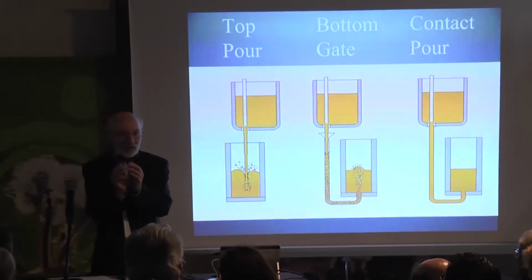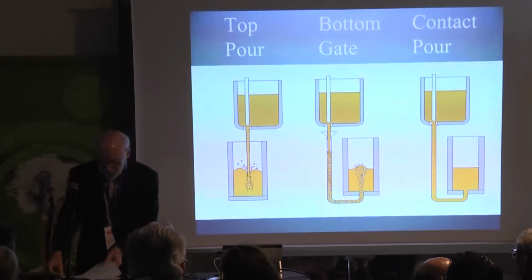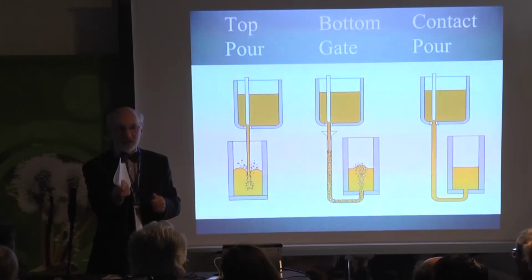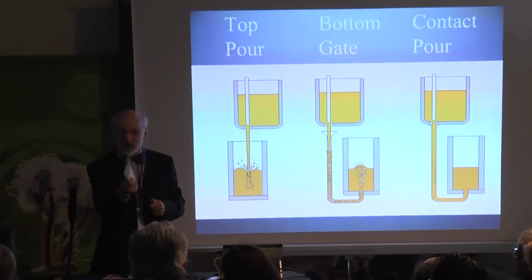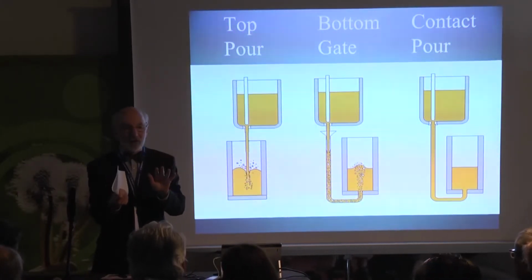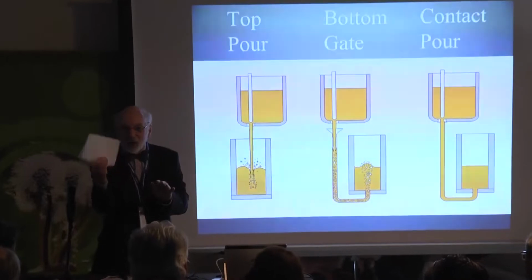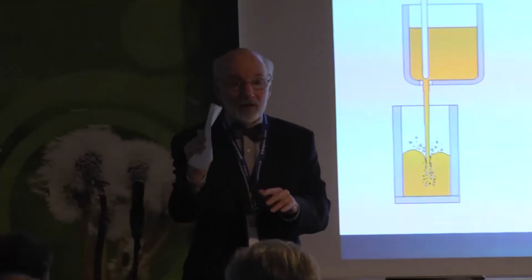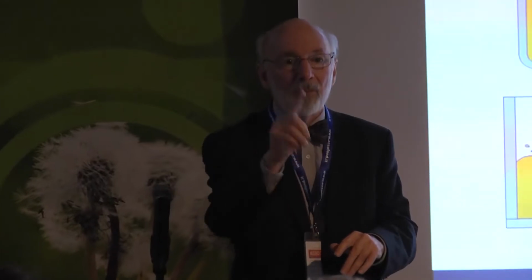Now, in my view, although the bifilm is a bad defect to have because it's a crack which you don't know is there, it's too thin, you can't see it, so this is an evil thing to have in your casting, and you will have thousands or millions in your casting. But the bubble is even worse, because the bubble makes a bifilm crack 1 meter long every time, depending on how big your casting is.